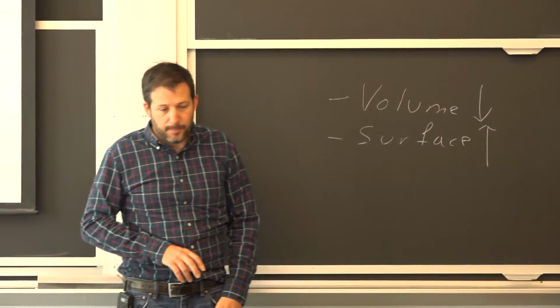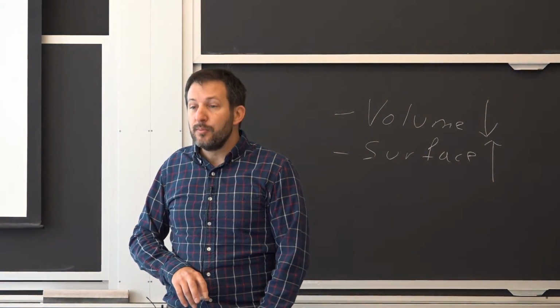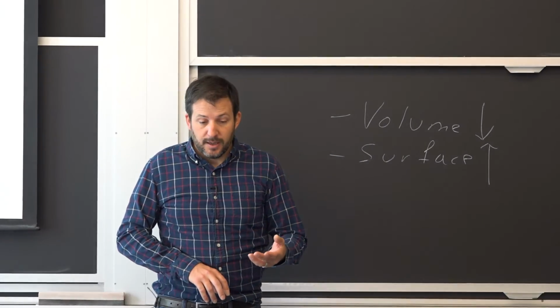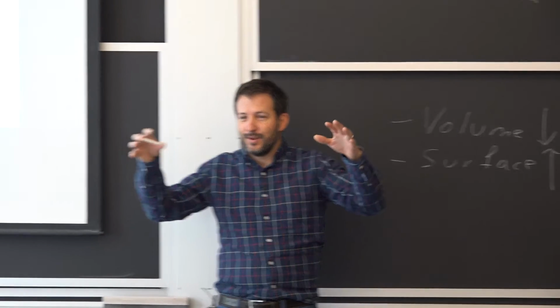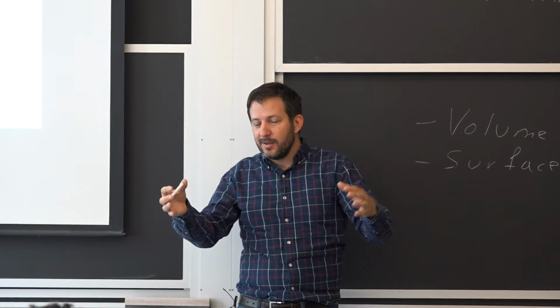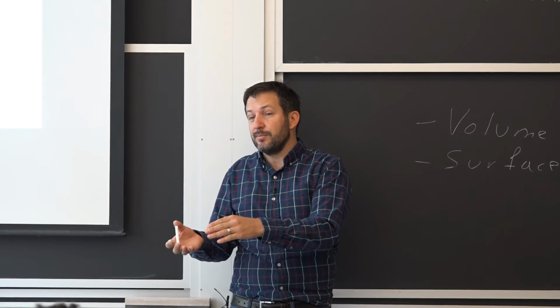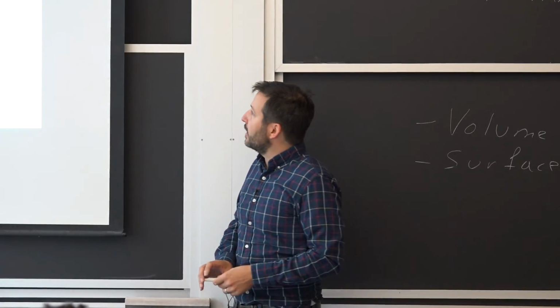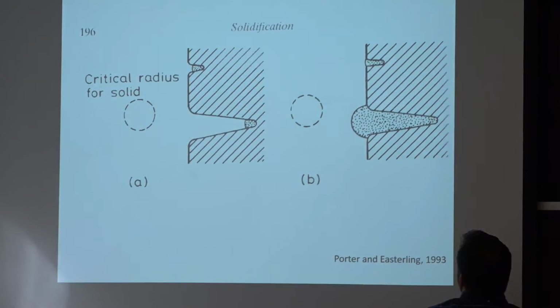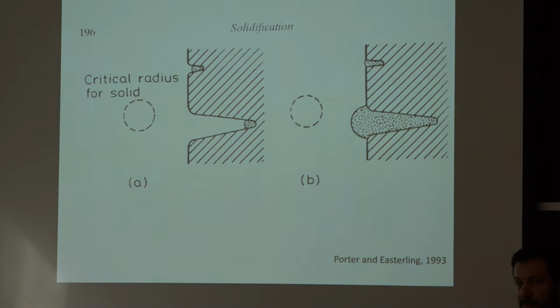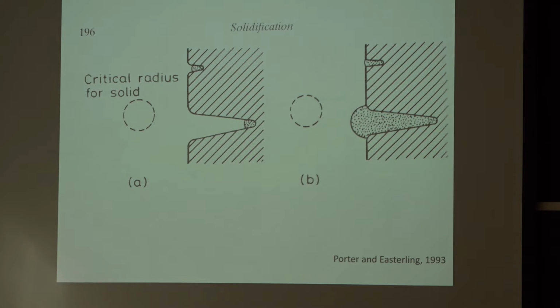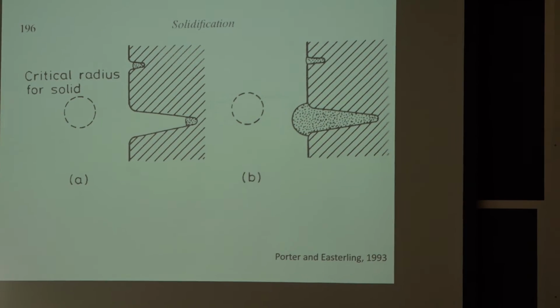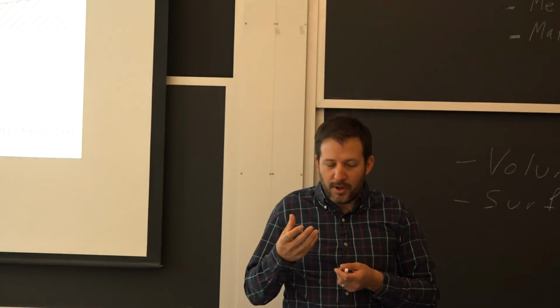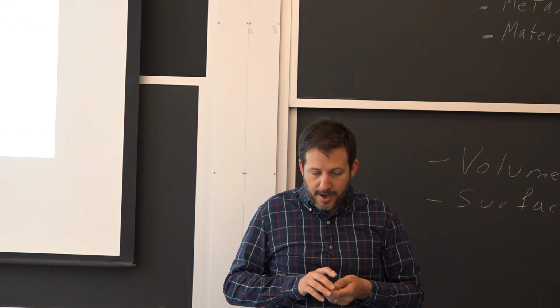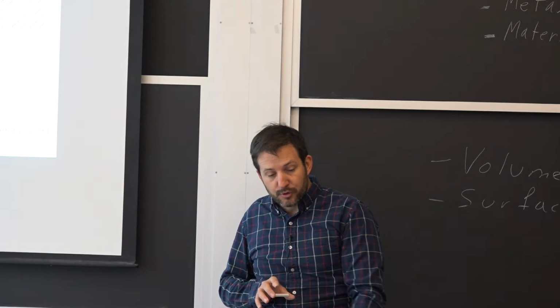So what happens? For metal, it starts from the mold. And the reason for that is when you have your pool of liquid metal, there is always an interface already between the liquid and the mold. That's high energy to begin with. So when you start to nucleate there, you're replacing essentially a liquid to solid interface with a solid to solid interface. That's great. It's the same way that you get snow or ice formation on the window as opposed to cubes of ice out of the air: there's a site for nucleation on the mold. It's extremely important for metals, not so much for plastics.